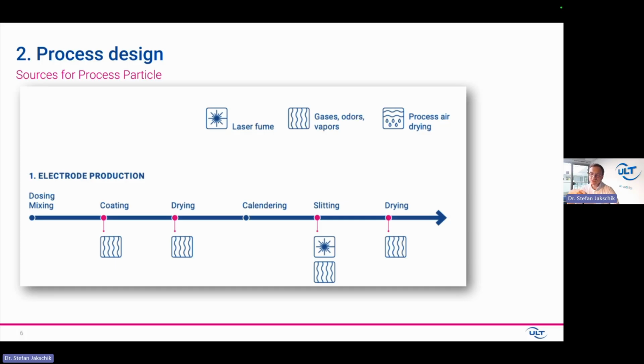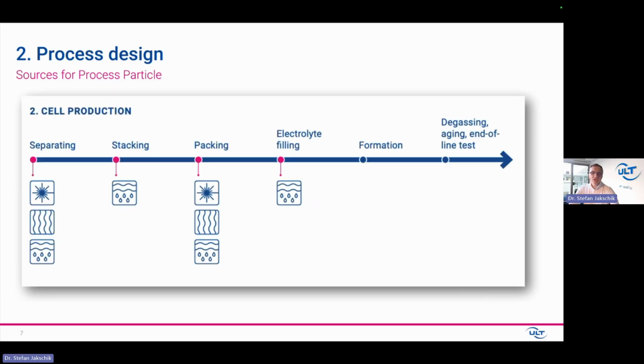The laser produces very small particles. I have some pictures of these later on. These are particles which need to be taken care of during the production. When moving on to separation, stacking, packing, filling, you also have the same kind of critical steps. Separating is nowadays done by a knife or laser. Especially laser produces these very fine particles, and you have to be aware of moisture in these steps.